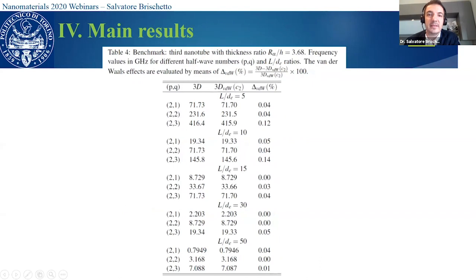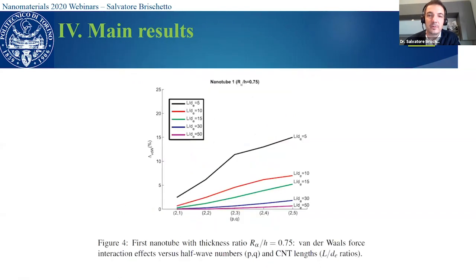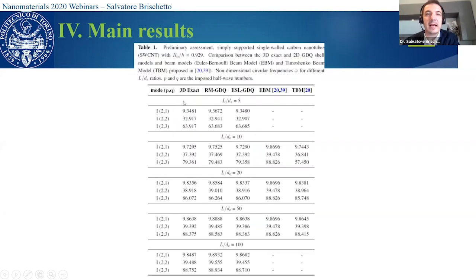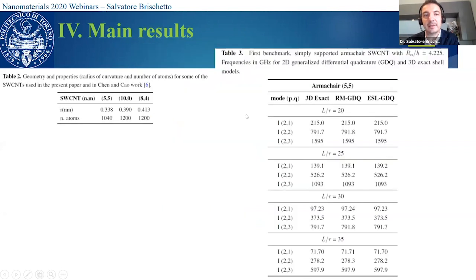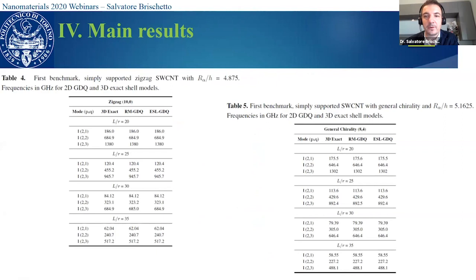Okay, similar results. So we can see here the van der Waals effects increase with the order of frequency, and it is more important for short single-walled carbon nanotubes. These are other similar results for carbon nanotubes and the comparison with the GDQ model by Professor Tornabene. And we can see the difference between a three-dimensional shell model and two-dimensional shell models and beam and the related beam models. So we have several results of this type.